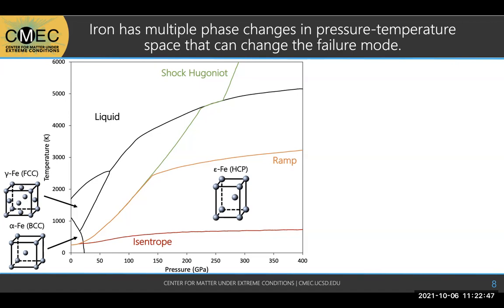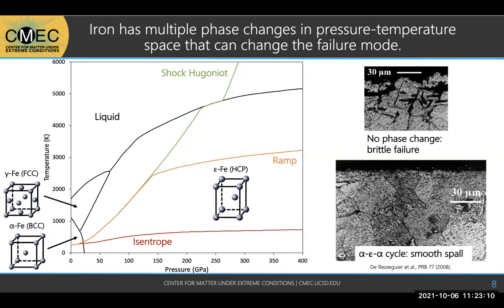But in spall, because you have that region of tension where you kind of release the pressure, the structure actually reverts back to the alpha phase. So you have this cycle, you go alpha, epsilon, alpha during spall. And next. And so this is where the change in failure mode can occur.